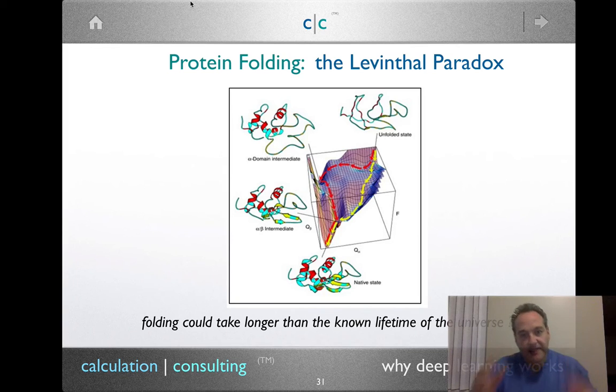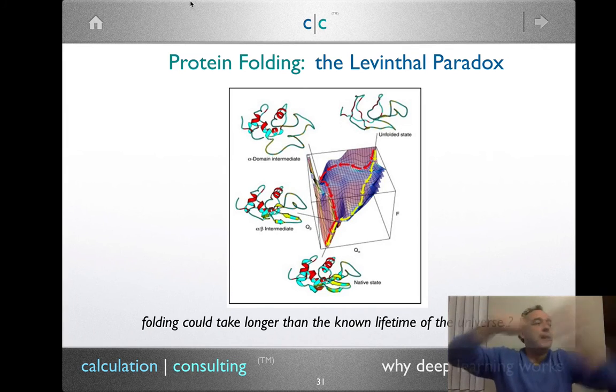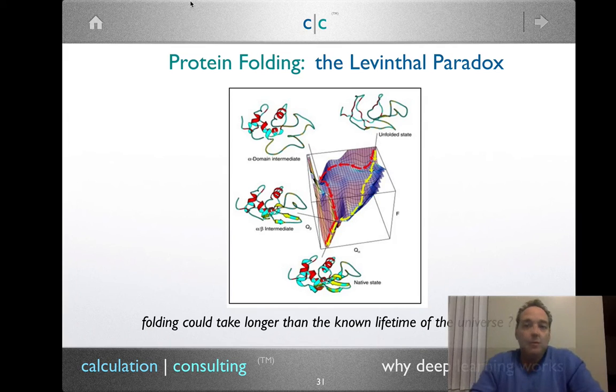And the idea is that in a protein, you have sort of this string, this polymer, and it has to fold into these different configurations. And if it were just folding randomly, or if it were just a random spin glass, the folding time of a polymer would take longer than the known lifetime of the universe. So clearly, polymers and proteins are not described by simple spin glasses. They're not simple p-spin spherical glasses. That's not what's going on.